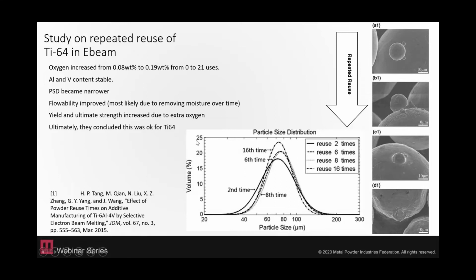So not only did those fines go away, but they did see a little bit of reduction in their larger powders. Their flowability did improve, and they think that that was likely due to removing moisture over time, but it could also be due to removing those fines. And then they did see changes in properties and actually an increase in yield and ultimate strengths due to the extra oxygen. Ultimately, in this study, they concluded that recycling this powder was okay for Ti-64.